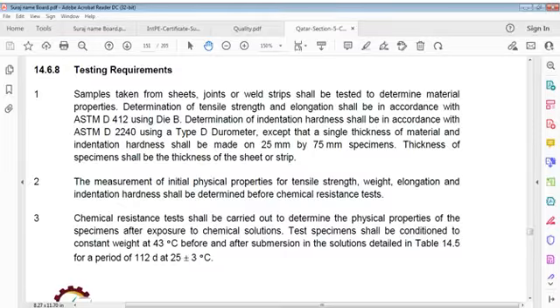Determination of indentation hardness shall be in accordance with ASTM D2240 using a type D durometer, except that a single thickness of material and indentation hardness shall be made with a 25 mm by 75 mm specimen. Thickness of specimen shall be thickness of sheet or strip. Measurement of initial physical properties for tensile strength, weight, elongation, and indentation hardness shall be determined before chemical resistance tests.